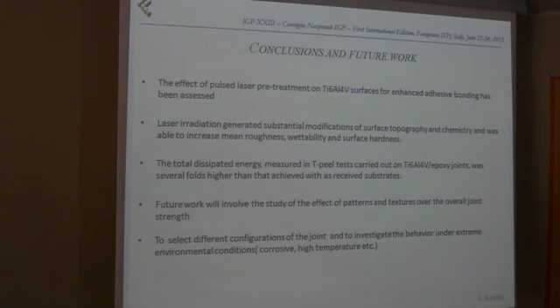So just concluding my speech, I reported the experiments on titanium 6-4 treated by laser, and we applied the laser treatment to the final application of adhesive bonding. As future work, we would like to study also the effect of different patterns over the surface, and if the crack propagation can be arrested with particular kinds of textures.